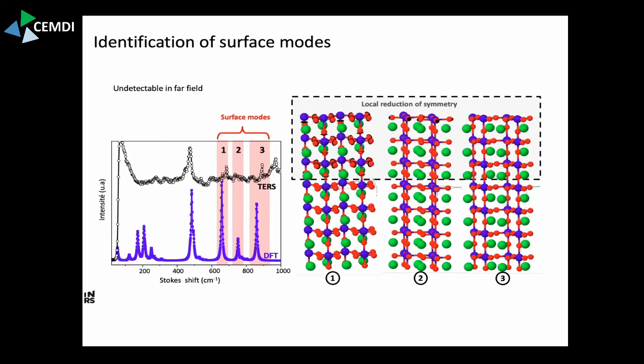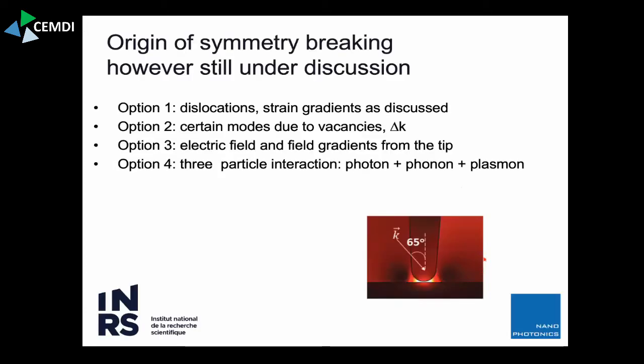Again, it's self-consistent. The numbers of the peak position kind of add up. They correspond reasonably well. And TERS, this tip-enhanced Raman spectroscopy, has a very low penetration depth. So actually, yes, we are very surface sensitive. So the good news was we see modes that were previously inaccessible by Raman spectroscopy. We're actually able, if this is correct, to see modes of oscillation in the surface. The less comforting news was we also see modes that shouldn't be there. And so this is the open discussion now that is also bringing into what's in literature.